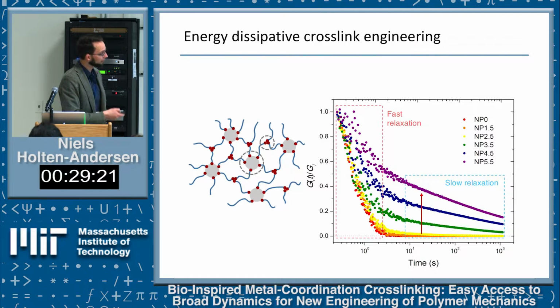So again, these are stress relaxation plots. This NP0, recent data, has no nanoparticles, only metal ions, and it relaxes on the order of tenths of seconds. The more nanoparticles we load into the material, the more this slow relaxation on long time scales becomes dominant. This just shows that the more particles you have, the more solid-like the material becomes.